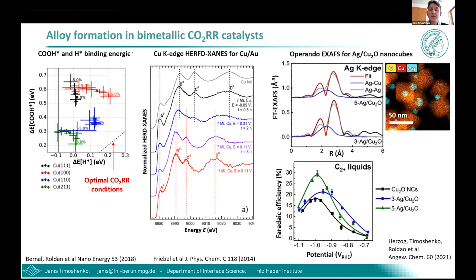And again, the presence of such bimetallic structures should not be taken for granted, especially for systems like silver-copper, where, unlike the copper-gold system, the miscibility of silver in copper is quite low. So we cannot really be sure in advance that there will be any meaningful amounts of copper-silver alloy present in our sample under working conditions.